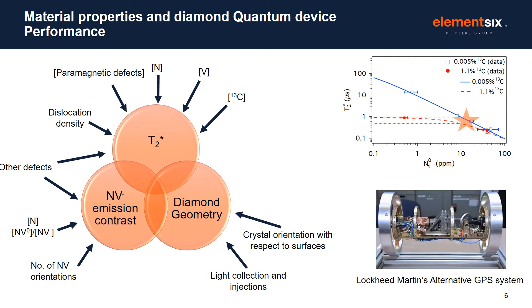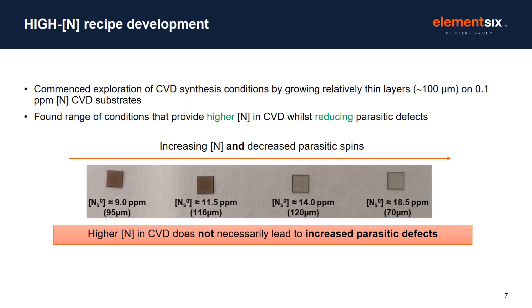We've been recently working at producing material in the 10 to 20 parts per million range for an application with Lockheed Martin for alternative GPS systems. So now I'm going to talk about how we've gone about optimising this 16 parts per million nitrogen material. Typically, when you add nitrogen to the CVD process, it introduces other defects that result in broadband absorption features, giving rise to material that looks brown in colour. These additional defects can limit the spin coherence time. We therefore looked at a range of different synthesis conditions, growing thin layers of material so we could rapidly feed back on the synthesis process. And we were able to show that we could reduce the concentration of these parasitic defects while actually increasing the nitrogen concentration. You can see this clearly in the colour of the samples in this series of diamonds.